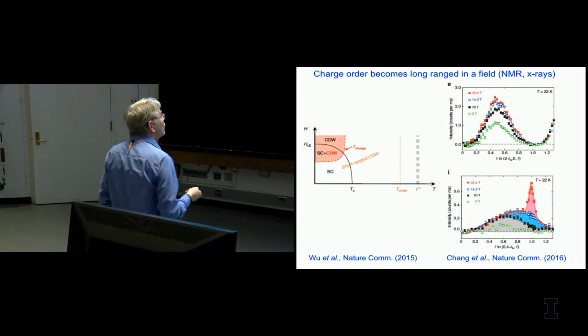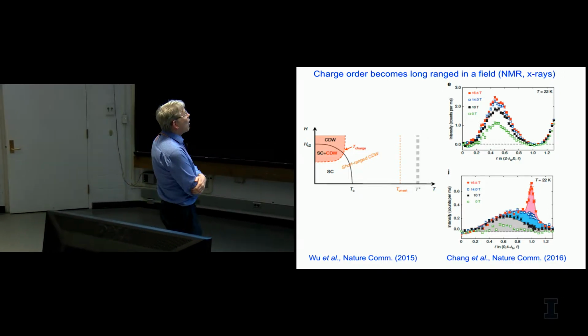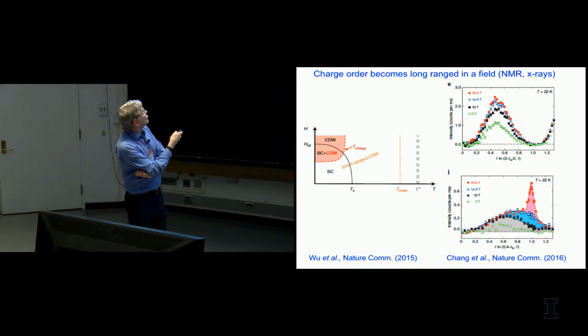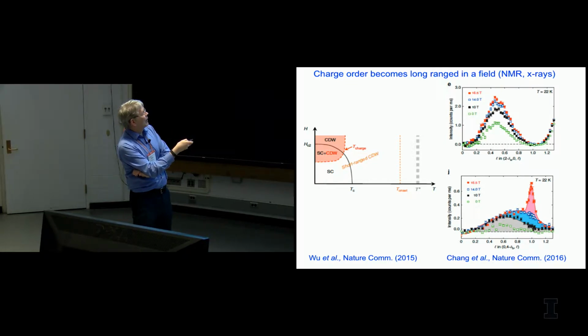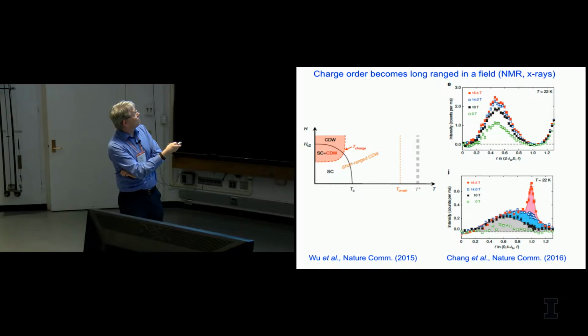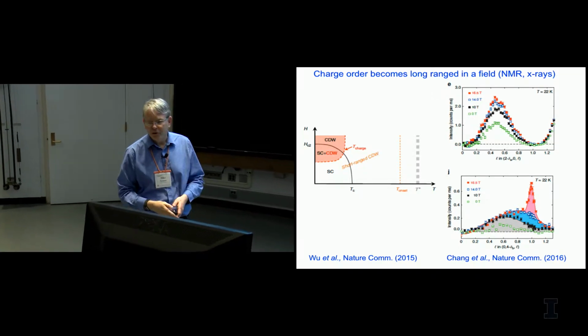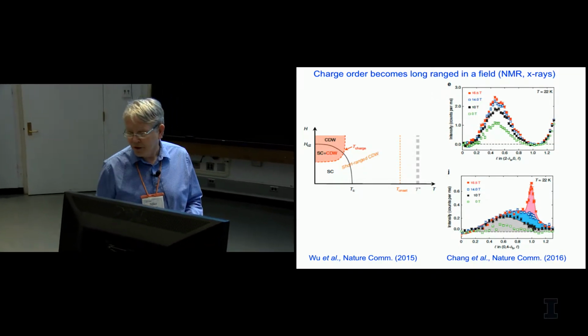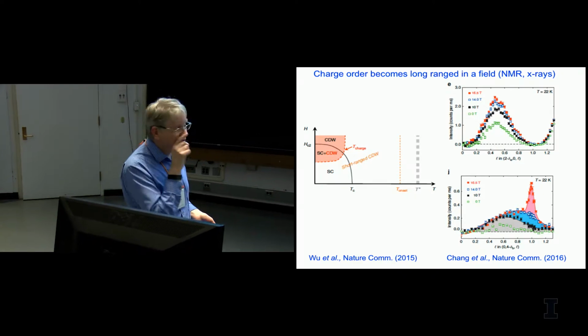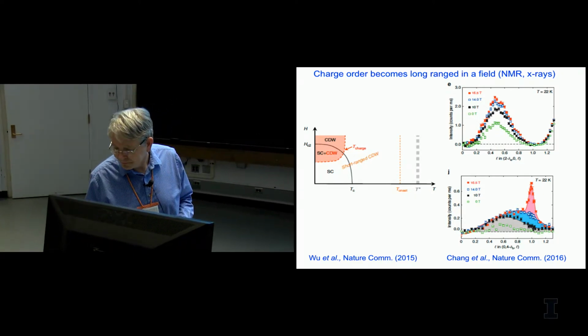What is now known is if you go to high magnetic fields, you actually get long-range charge order, which is interesting. This long-range charge order has the same in-plane wave vector as the short-range order, but it has a different out-of-plane wave vector. So the short-range order happens at L equal 1/2, and the long-range order happens at integer L. And this has been seen also by NMR experiments, and we know this is a thermodynamic transition. It's been seen by ultrasound.